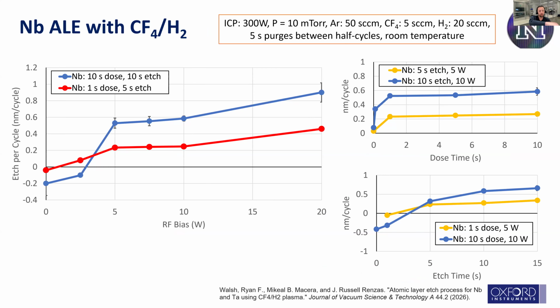We also look at this on the upper right as a function of dose time. We want something where our etch per cycle is stable as a function of dose, so it's a self-limiting ALE process. We found we had saturation at about 1 second. Similarly, on the lower right, we want something where, with etch time, we're not getting continued spontaneous etch. Similarly, if we're too low and don't do enough etch time, we're still in this polymer removal stage.